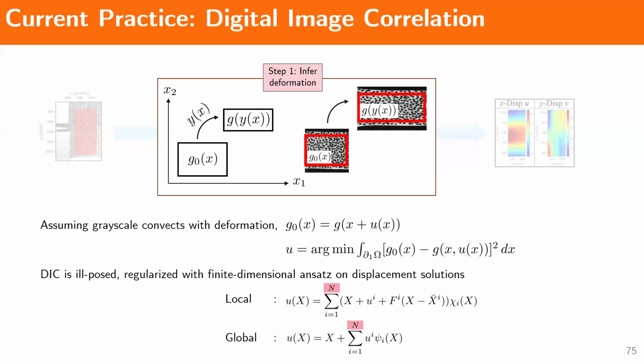In fact, when you actually go ahead and do experiments with DIC, what you often see is that when you have a complex state in your material, when you have holes near the boundaries, near the edges, your displacement solution from this method tends to be really sensitive to these regularization parameters. So if you vary your subset size a little bit, or vary how many basis functions you're using, you get a different displacement solution, and it gets more and more sensitive when you have complex states in the material. And that is not really good, because complex states of the material is when you're sampling non-uniform strain states in your material. So that's when you usually would get the most information to back out a model from.